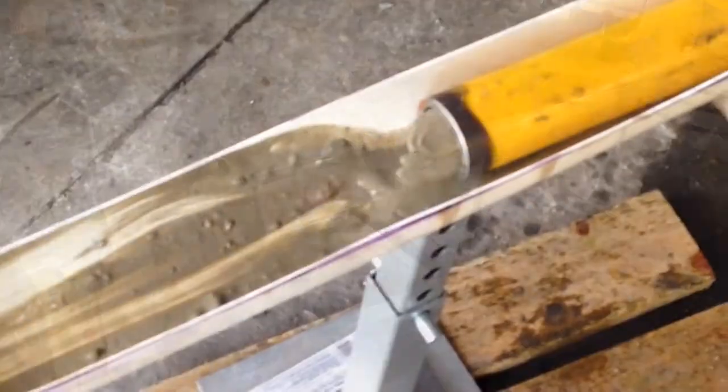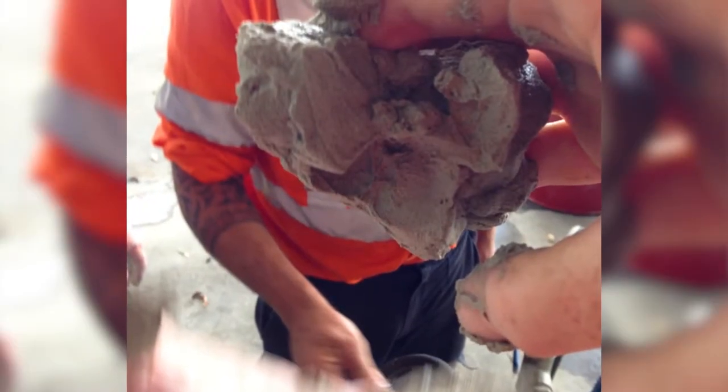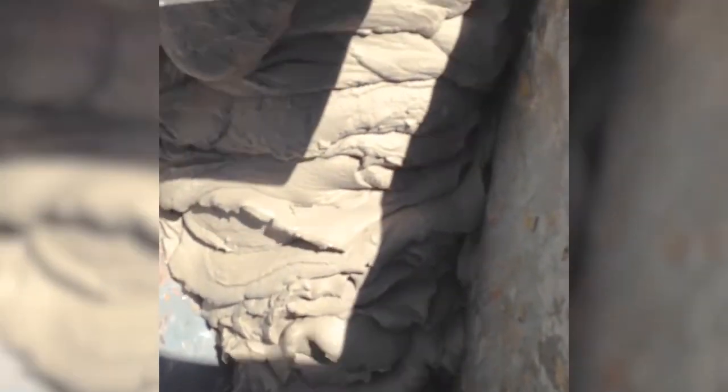I had to make a concrete with a density just above the density of water. I had to make the concrete such that it wouldn't wash out when it was pumped through a water column. And thirdly, I had to make it in such a way that it would bridge large areas where there may not be anything to support it. So it was quite a technical exercise. Its viscosity was critical, and we also had time constraints. The physical properties were about 10 MPa compressive strength, which was satisfactory if you had a depth of approximately a metre to support any amount of ordinary strength concrete above it.